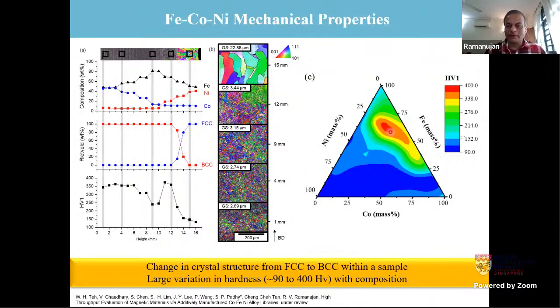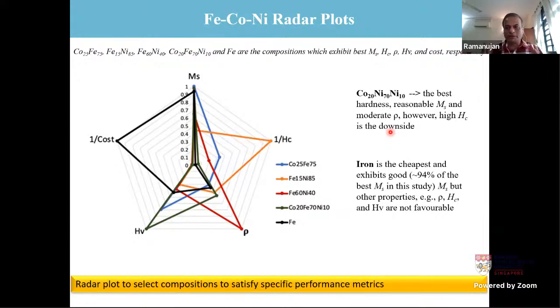We could also relate it to grain size so that we have some kind of rationalization of why this kind of behavior is observed. So from all this information, we can plot what are called radar plots or spiderweb plots, which can quickly identify which composition has a good combination of properties. So if you want a single property, for example, MS, then you can identify which compositions have the best single property. But if you want a combination of properties, you can also identify using this radar plot materials that have reasonable MS, reasonable HC. So you can play this combinatorial game using this type of methodology. So this is an example of how we have used accelerated methodology to satisfy certain property metrics using additive manufacturing as the technique for sample prep.